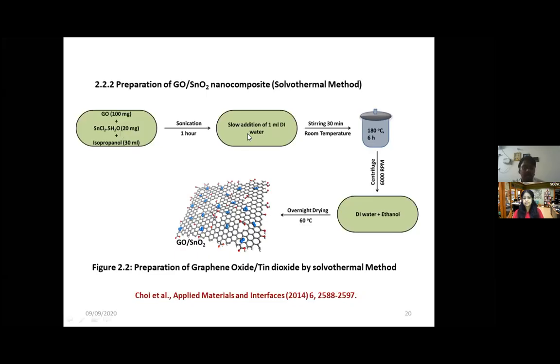Then we slowly added 1 ml of DI water while stirring for 30 minutes at room temperature. This solution is transferred to a 50 ml Teflon-lined autoclave, and it is maintained at 180 degrees Celsius for 6 hours in a muffle furnace. 180 degrees Celsius for 6 hours. After cooling down to room temperature, we again transfer it to a 50 ml centrifuge tube, centrifuged at 6000 rpm in the presence of DI water and ethanol. The nucleated nanocomposite, that is the GO-SnO2 nanocomposite, settles at the bottom, with unreacted metallic salts at the top. It is dried overnight in vacuum at 60 degrees Celsius to obtain the material GO-SnO2. This is an amorphous black powder. So this is our first sensor material.